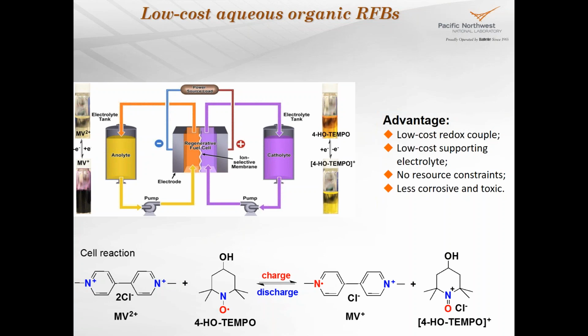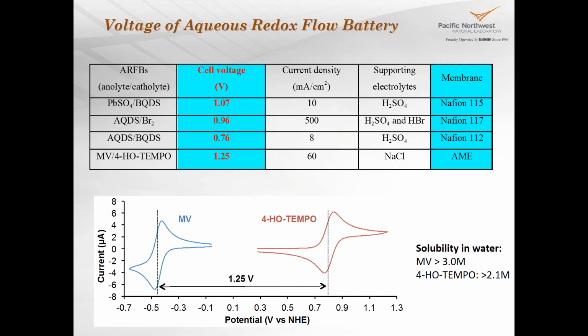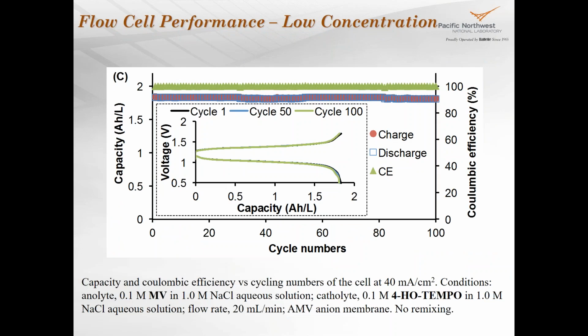I'm showing a little bit of performance of this system. You can see the voltage is about 1.25 volts, similar to the vanadium system. Also, compared to other organic systems, we use an anion exchange membrane instead of Nafion, which will bring down the cost of the membrane quite a bit. Some of the performance data here show 100 cycles, this is test data at low concentration, with 100 cycles, very good capacity retention capability, and the Coulombic efficiency around 100%.